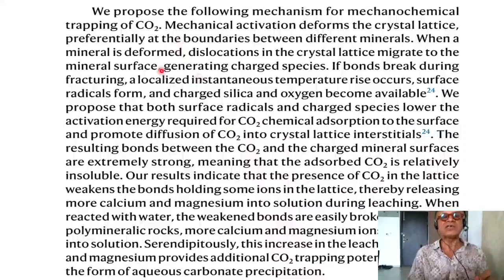In the discussion, they say we propose the following mechanism for mechanochemical trapping of CO2. Mechanical activation deforms the crystal lattice, preferentially at the boundaries between different minerals. This is where polymineralic rocks play a critical role. When a mineral is deformed, dislocations in the crystal lattice migrate to the mineral surface, generating charged species. If bonds break during fracturing, a localized instantaneous temperature rise occurs, surface radicals form, and charged silica and oxygen become available. We propose that both surface radicals and charged species lower the activation energy required for CO2 chemical adsorption to the surface and promote diffusion of CO2 into crystal lattice interstitials.